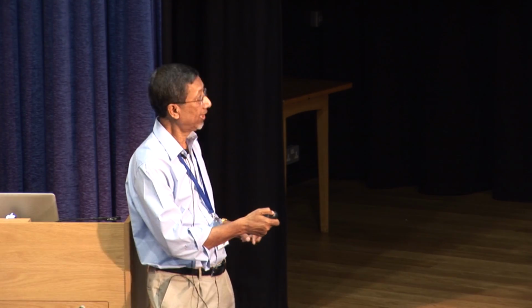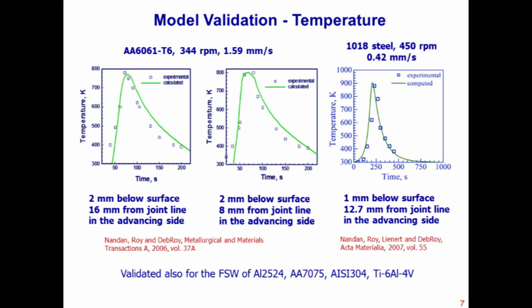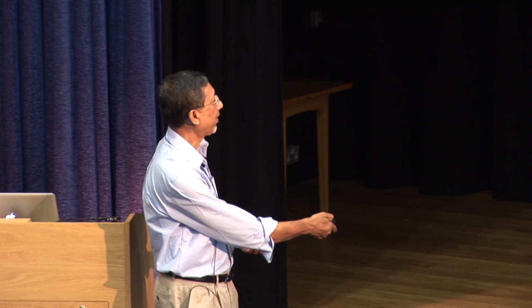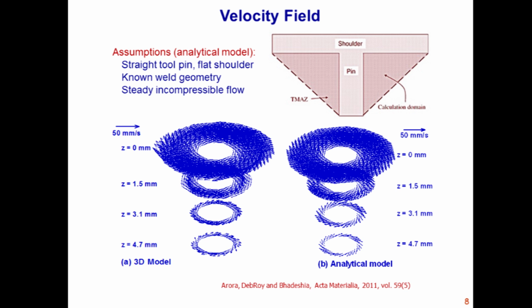So the point here is very different thermal properties and very different mechanical properties. Both are important for these calculations. And in each case, we seem to be able to reproduce the thermal cycles at monitoring locations reasonably accurately. That's the issue. All right. So temperature fields, we can measure temperatures, and we can compare the calculated values with the measured values to see how good the calculations are.